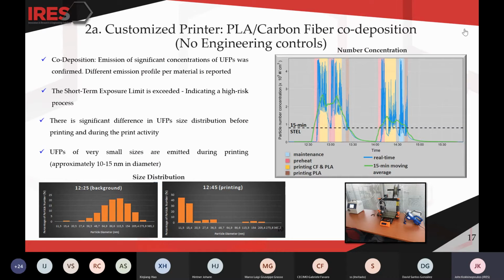If we continue, we can see the second campaign. This campaign consists of 2 measurements during the operation of a customized printer for the co-deposition of PLA, polylactic acid, and carbon fibers. First, we will analyze the case without any engineering controls at all. As you can see from the diagram, the 15-minute moving average, represented by the green line in the graph, exceeds the recommended short-term exposure limit during the whole process, reaching values as high as 3 times the limit.